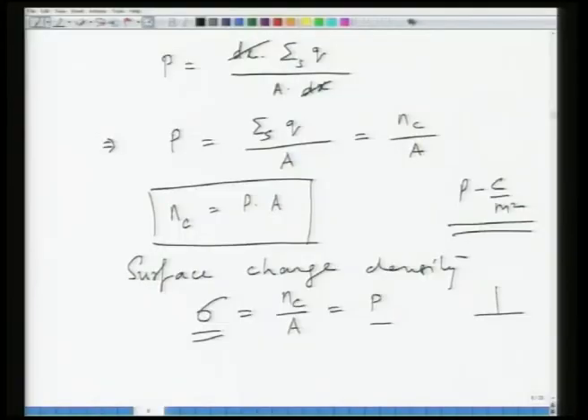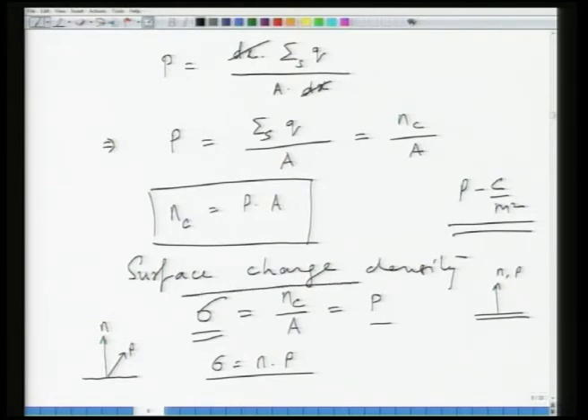Now, we are taking sigma to be equal to P, assuming that sigma and P are in the same direction. If this is your surface and this is your surface normal, then P is also along this direction, assuming that. However, if your surface was this, and surface normal was this, and P was that, then sigma would be n dot P, where n is nothing but the outward pointing vector which is normal to the surface of a polarized material. So, the key concept here is that we have looked at polarization more deeply, and what we have established is that polarization of a material is nothing but surface charge.